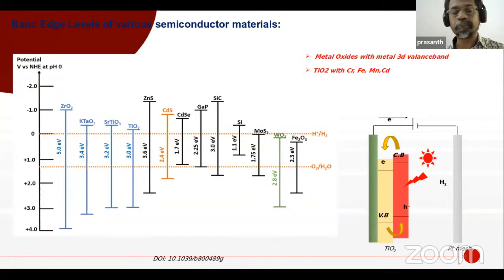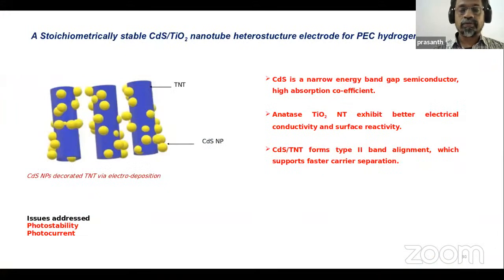Heterostructure formation depends upon band alignment, then the crystals, what's called the lattice parameters, because if the lattice parameter is too different, then it will feel a strain. So the percentage of strain will go up. That will make a strained band alignment, band structure at the interface. So that interface will lead to a carrier loss. So by making a heterostructure, you have to be careful with many such engineering parameters for making band structure.